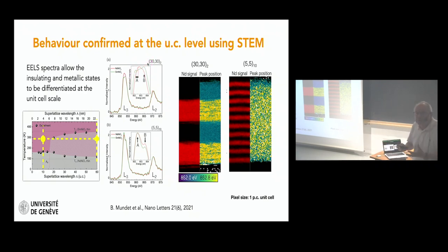So we use this contrast in a color map, and you see here for the 30 unit cell, this is now the composition, and this is this class analysis, so that you see that the two layers have different behaviors. The neodymium is metallic, the other one is insulating, but when you go to the 5,5, you have a uniform composition, which shows that at the atomic scale you can verify that both layers are indeed metallic.